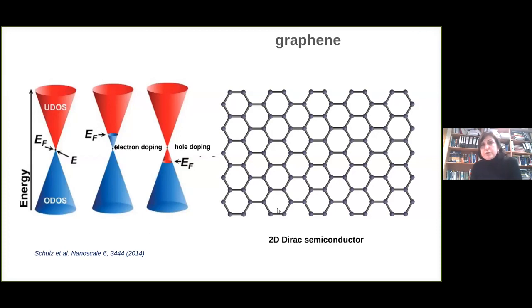So we want to make use of these features now when we study these heterostructures with graphene. But what I want to show to you is when I'm going now to bring these two systems together, it's going to be a win-win situation for both, for ruthenium trichloride, but as well as for graphene. Because depending on the work function of ruthenium trichloride, I'm going to expect that there will be a charge transfer between ruthenium trichloride and graphene. So I'm going to basically dope graphene. And that will mean that one is going to expect that the conduction properties of graphene are going to improve.